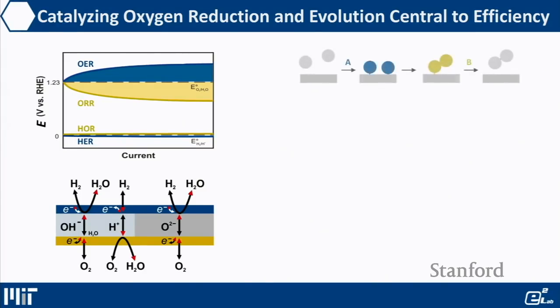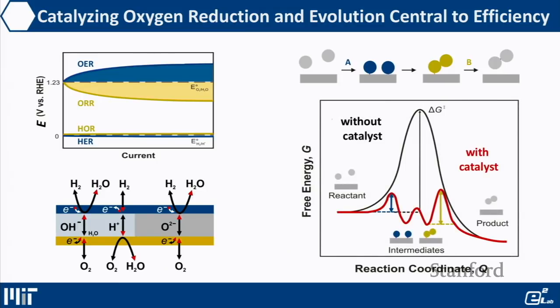So back to the kinetics. We said that oxygen reduction and oxygen evolution are very difficult, and the consequence is that if you operate a hydrogen-oxygen fuel cell, you can have significant voltage loss, or energy loss, for the device when you run at a finite current. If you look at voltage as a function of current, the shaded area on top comes from the losses associated with reduction of oxygen and evolution of oxygen, while hydrogen redox chemistry is very efficient. Now imagine if you're going to use nitrogen or CO2, we'll have comparably large energy losses. So the overall device will bear very little energy.